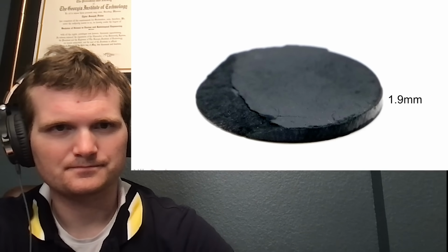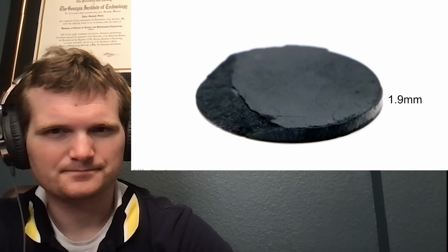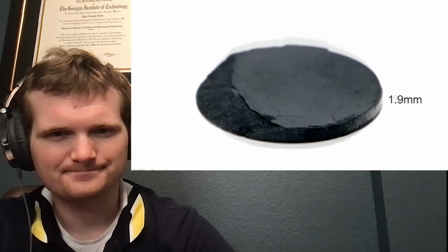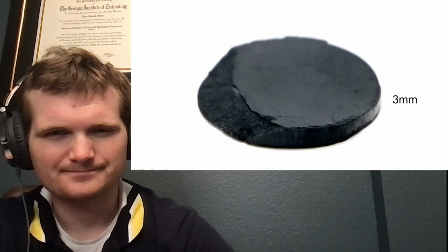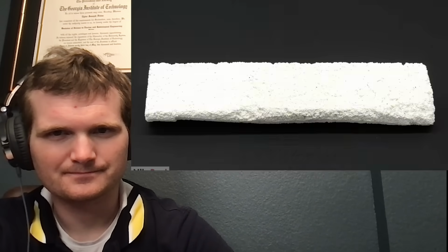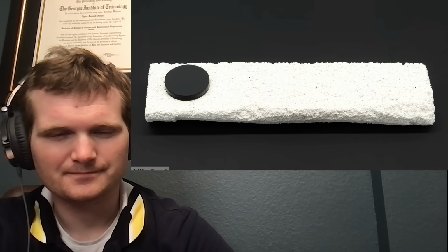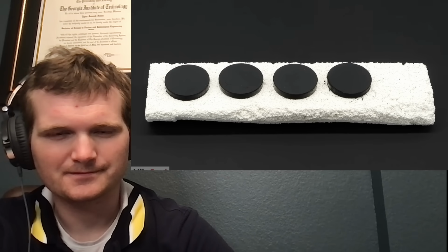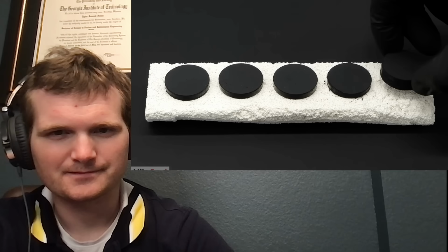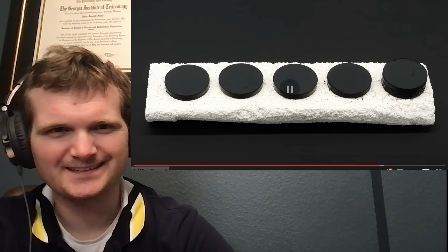The 1.9 millimeters did seem to be okay, but I felt that it was just a bit too thin and fragile. So, I decided to make it 3 millimeters instead. I also found that spacer piece that I was missing, and I was able to make some really nice pellets. After making 4 of them, I decided for the last one that I would make it a lot thicker.